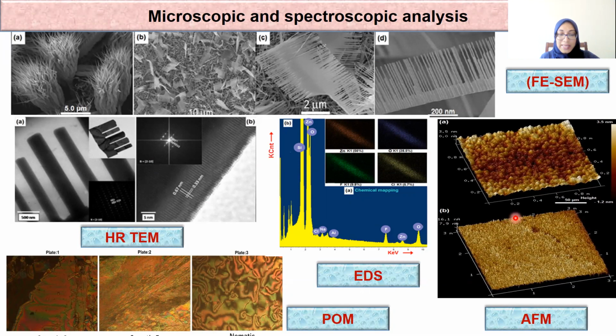The AFM results, as shown in this figure, indicate that the films are exceptionally rough, dense, and they are not homogeneous in nature. The surface roughness governs the way that the nanomaterial interacts with external parameters such as light, doped materials, etc., and thus ultimately determines the functionality and properties of the material. Here, the roughness was determined to be around 4.9 nanometer.